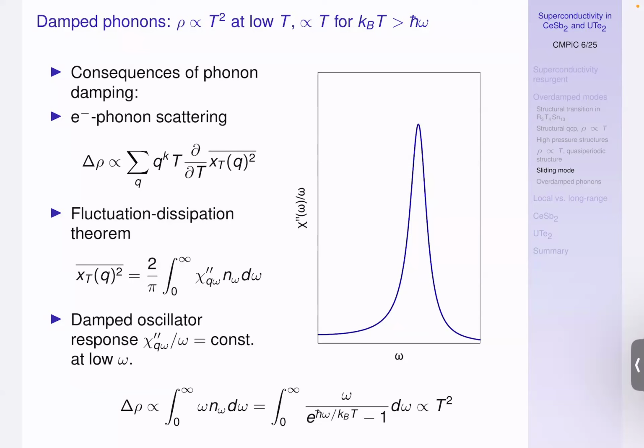All right. So if I now stick that into this formula to get x squared average, then I have in my formula omega, because pi double prime is proportional to omega at low frequency, omega times n omega, d omega. And you can just do a substitution here to see that, because this has this form, omega over temperature, you just see by power counting, this must be proportional to T squared. So you immediately get that for electron-phonon scattering, as soon as phonon damping becomes relevant, the low temperature resistivity should be proportional to T squared.